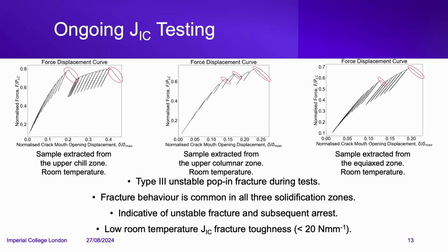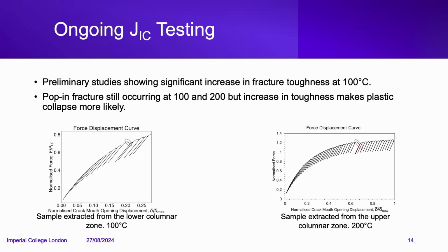But yeah, so the fracture behavior is common in all solidification zones, as you can see from the 3 force displacement curves here, and valid J1C values were able to be obtained, which were low, less than 20 Newton per millimeter. At higher temperatures, preliminary studies are showing, as to be expected, significant increases in fracture toughness. The fracture toughness is about 2.5 times the room temperature values, but you do still see pop-in fracture, though it's not as common and not to as high a magnitude.